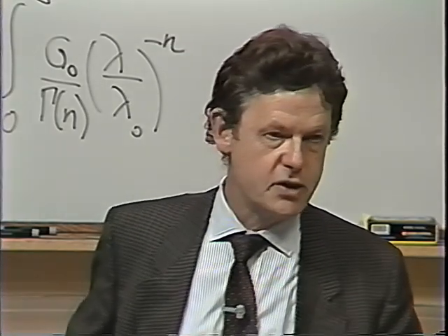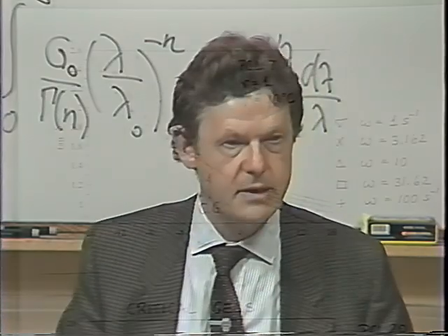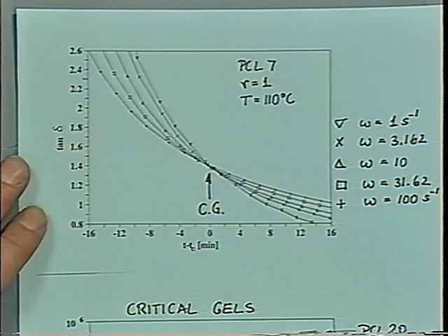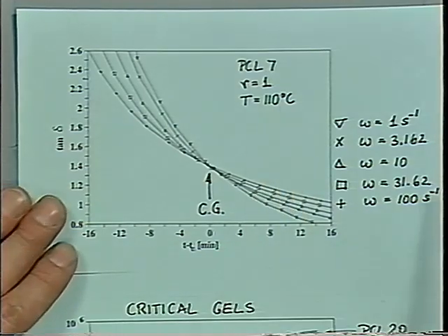Aki reacted the systems isothermally. This was a reaction at 110 degrees. He mixed the sample at 110 degrees using a solvent, and then evaporated the solvent, and then put the material in the rheometer. It already had started to cross-link at that time. So he found that at 110 the cross-linking rate is still low enough for our experiments.